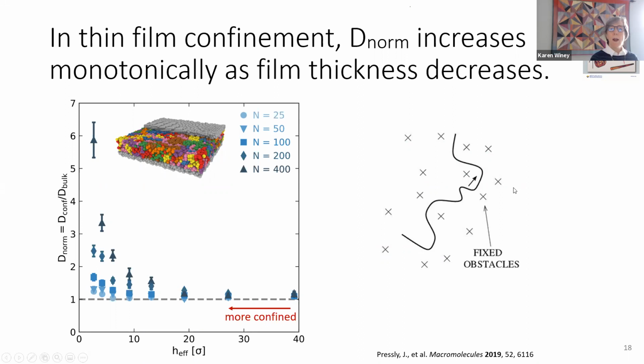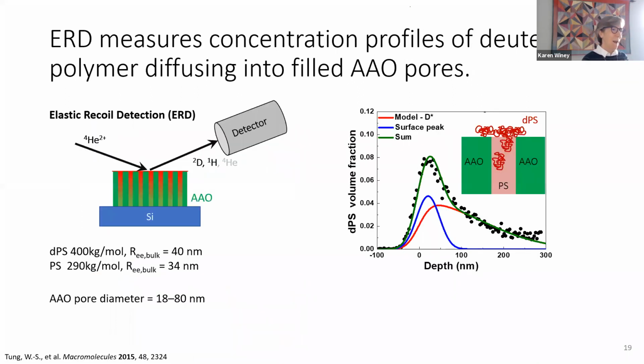Okay, so now I'm just going to insert the experiment, and the experiment is what we did first. We used a method called elastic recoil detection. Anodized aluminum oxide, or alumina templates, have very well-defined cylindrical pores, and we filled them up with polystyrene. Then we put a thin layer of deuterated polystyrene on top and let that deuterated polymer diffuse in. Elastic recoil detection can separate out deuterium and hydrogen.